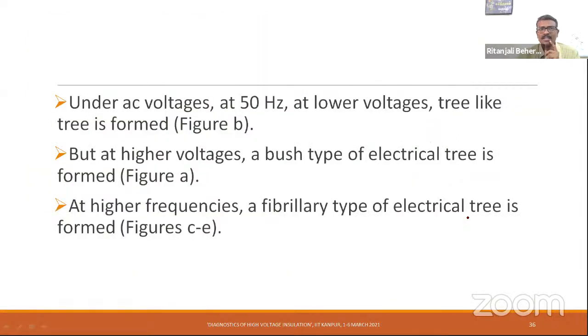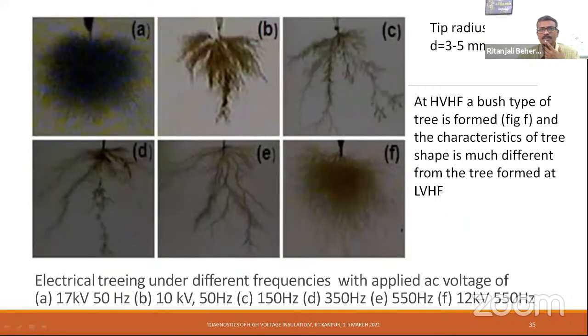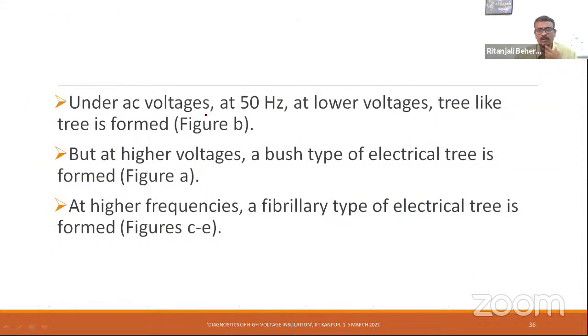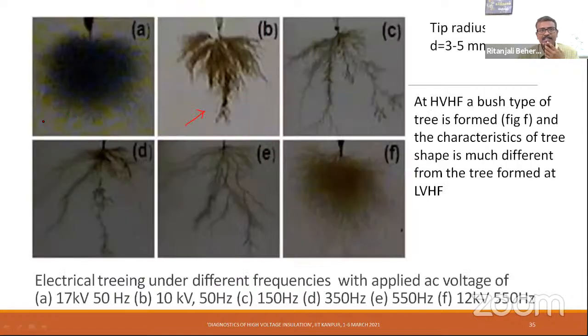So under AC voltages, which means at 50 hertz, at lower voltages, which means at 10 kV, a tree-like tree is formed. That is figure B. Whereas at higher voltages, a bush type electrical tree is formed. That is A. This is at higher voltage because this is at 17 kV and this is at 10 kV.